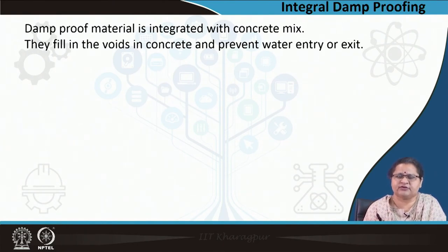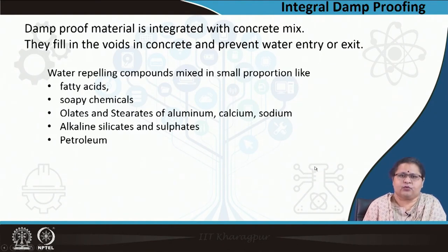They actually enter into the voids of the concrete and eventually prevent water entry or exit from a system. So, they are water repelling compounds like fatty acids, soapy chemicals, oleates and stearates of aluminium, calcium, sodium, alkaline silicates and sulfates, and even petroleum. So, these may be added in fixed amount. If you add more of it, then disintegration of the mother material may happen.